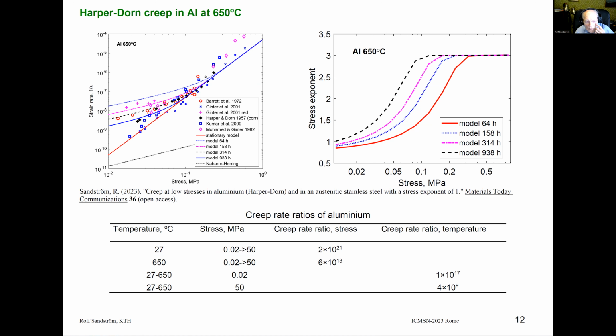The same applies to aluminium here. This is also a classical example, which could be quite confusing because people have thought initially that the stress exponent was 1, and some people got another result. But now this can be fully explained because the stationary creep result is shown here. So most results obey that. But if you take primary creep into account, you can explain the low stress exponent here. And this is also illustrated here, the plot of stress exponent versus stress. You can see that at very, very low stresses, you can get a stress exponent of 1. Otherwise, you get a stress exponent of 3, which is typical of more stationary conditions.